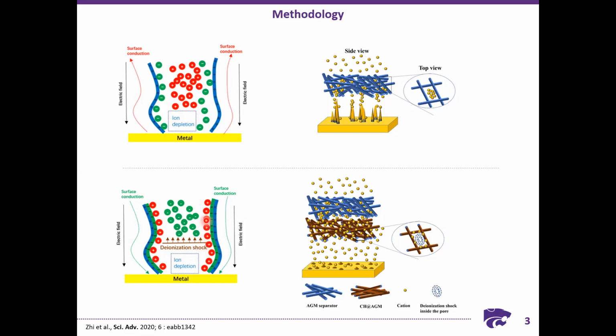So because of these two phenomena, what the authors expect is that the negative charges on the surface can control the deposition of lithium metal, which can regulate the deposition of lithium metal on the surface, resulting in the prevention of dendrite growth.